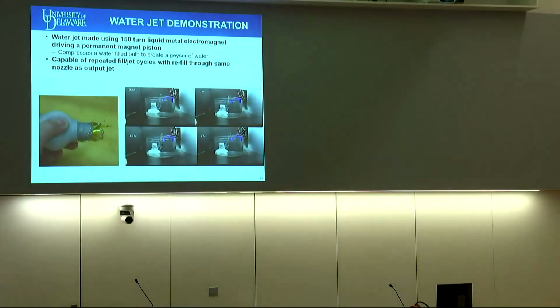And using this, we then showed that we could use this liquid metal electromagnet to drive a permanent magnet structure to compress a water bulb to create a geyser of water, and demonstrate the ability to repeatedly fill and jet through that same nozzle using this approach. And you can see the levels of current we're using is something like 1 to 2 amps. So within that range that we can reliably use for extended periods underwater. So again, a reasonable current level for extended use.